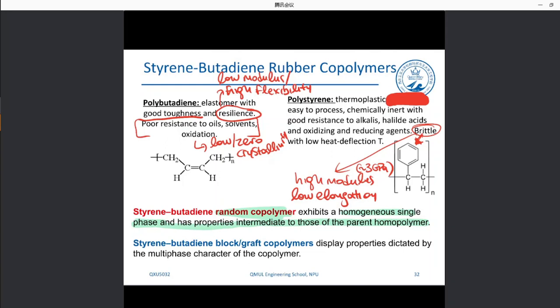And also we create graft copolymers, where the properties are controlled by the multi-phase character of the copolymer. And how do we control this multi-phase character? Essentially with the parameters that we set: the degree of polymerization, the composition of our material, and also by testing it at different temperatures.